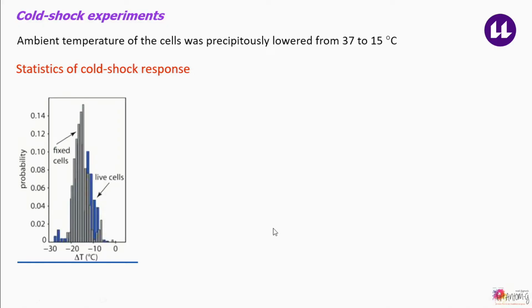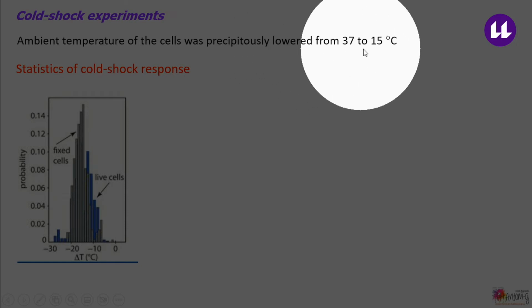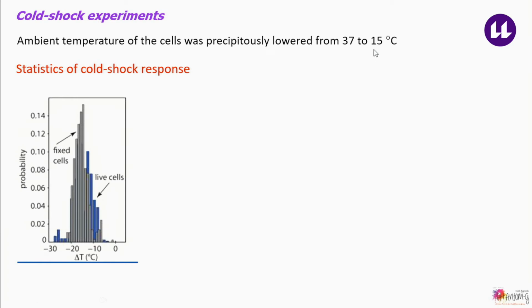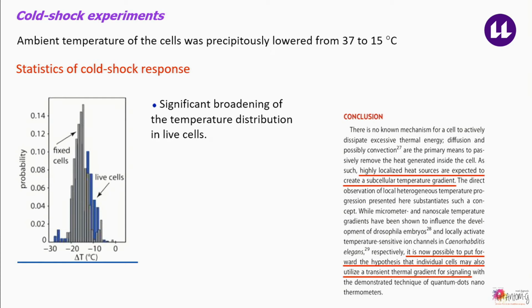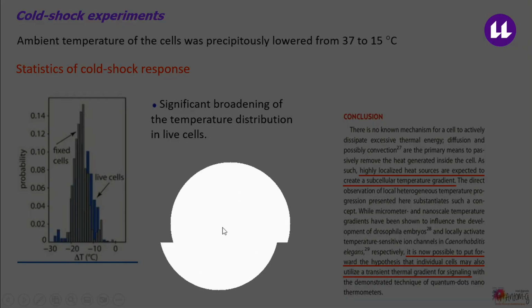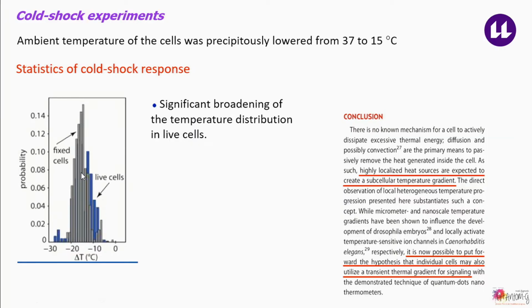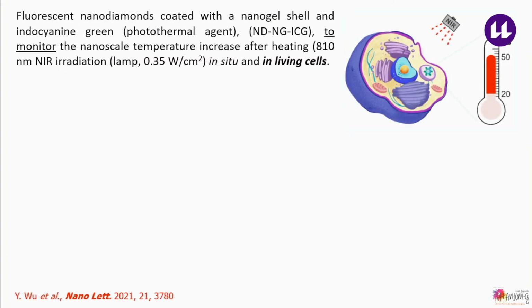And this also occurs after a cold shock experiment, so they suddenly lowered the temperature of the cell from 37 to 15, and what they have is a significant broadening of the temperature distribution in live cells. We can see here the temperature distribution in fixed cells is much, much narrower. Okay, second example of these